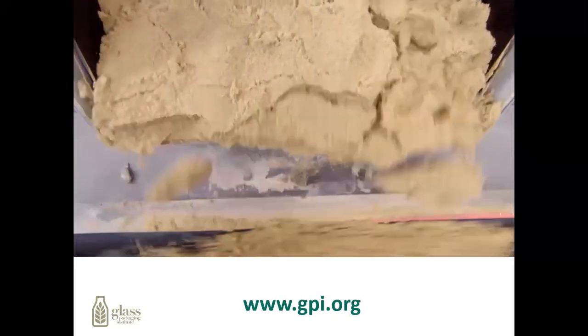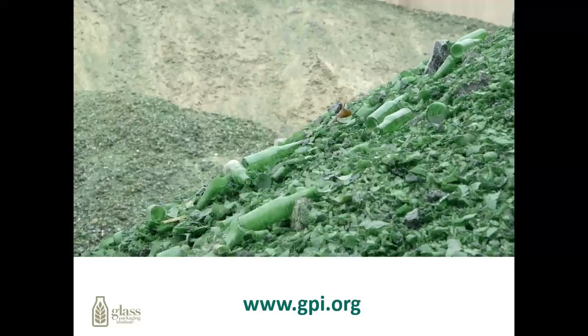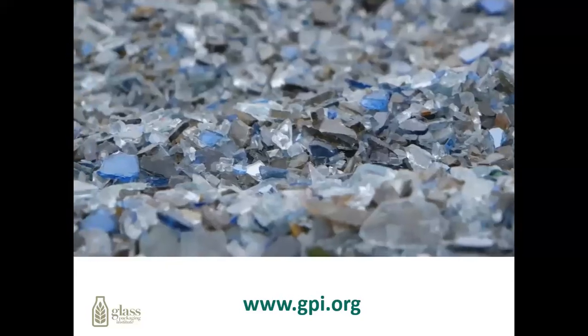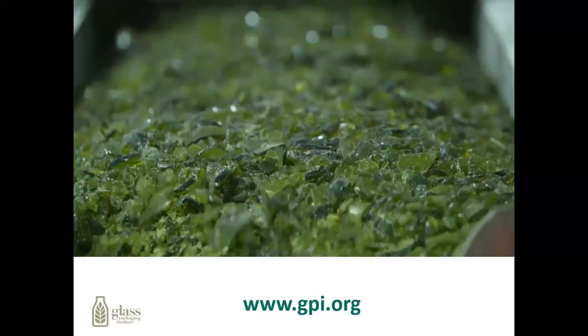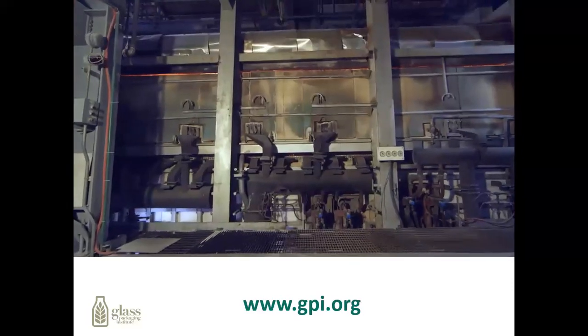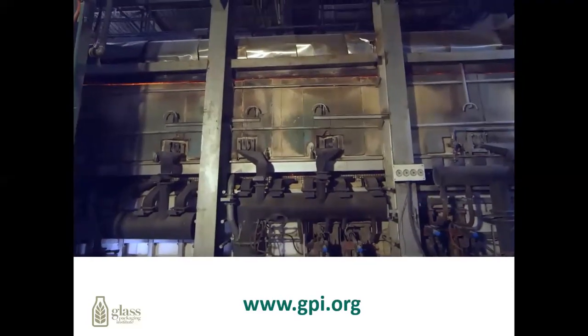We begin here — silica sand, soda ash, and limestone. Recycled glass from consumers, or cullet, is added, on average making up nearly 40% of the mix, and in some places 70%. And we bring it here: 2,850 degrees Fahrenheit — hotter than molten lava. This is the furnace. In a typical furnace, 10 tons of glass are formed every hour. The furnace feeds the refiner with a river of liquid glass.